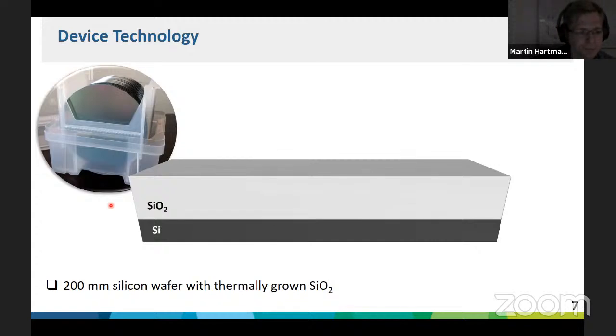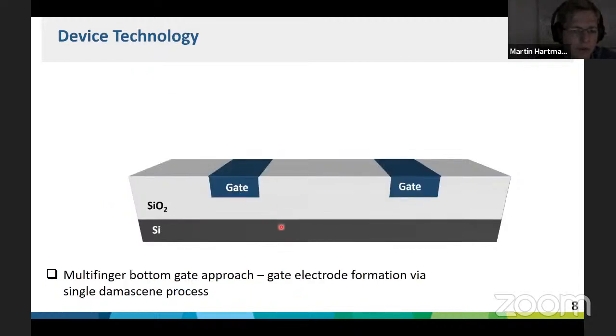And we do all our processes on the wafer level. So these are all wafer level processes. We don't do any pick and place also. This is not what we do. And we usually start with a silicon wafer. We grow some thermal oxide on top of them. And then via a Damascene process, we structure the gate electrodes.